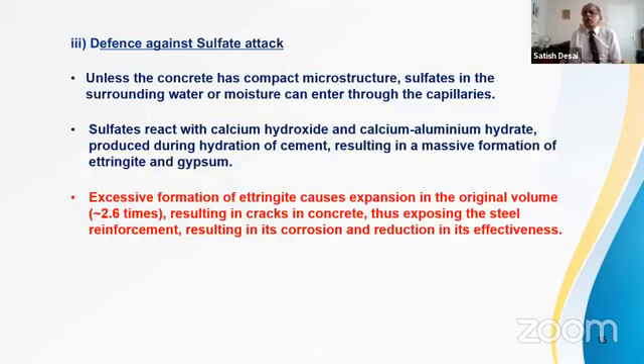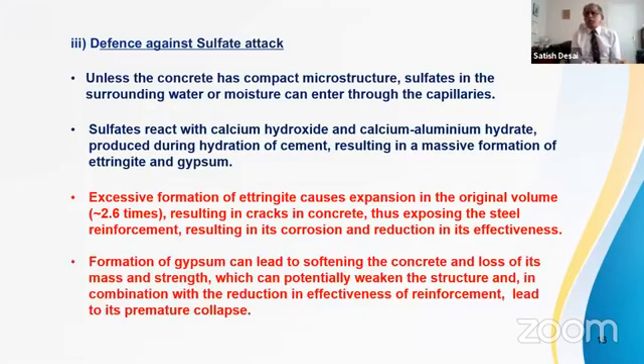Excessive formation of ettringite causes expansion of internal volume 2.6 times, 3 times. Concrete cracks, the surface cracks, steel is exposed. What happens? Steel gets corroded and its effectiveness is reduced. Formation of gypsum can lead to softening the concrete and loss of its mass and strength, which can potentially weaken the structure. And in combination with reduction in effectiveness of steel, what else can happen but premature collapse?